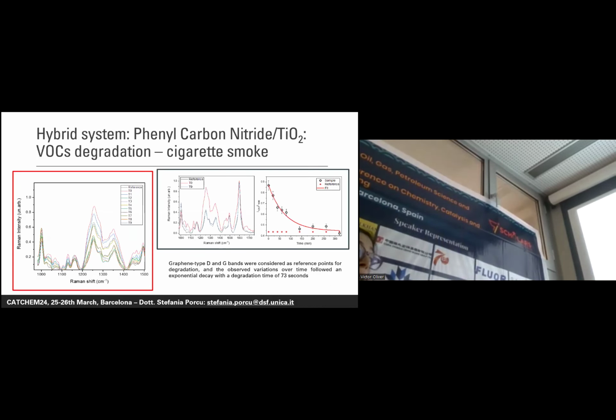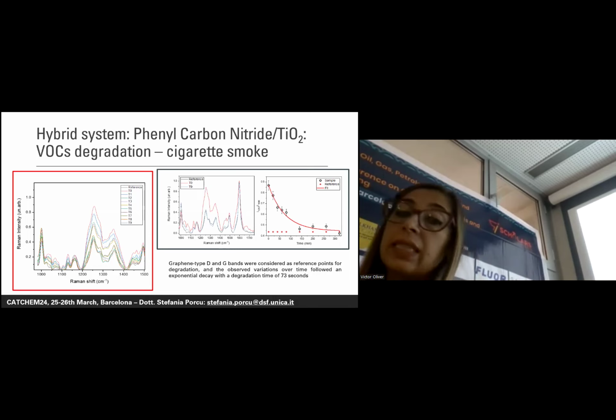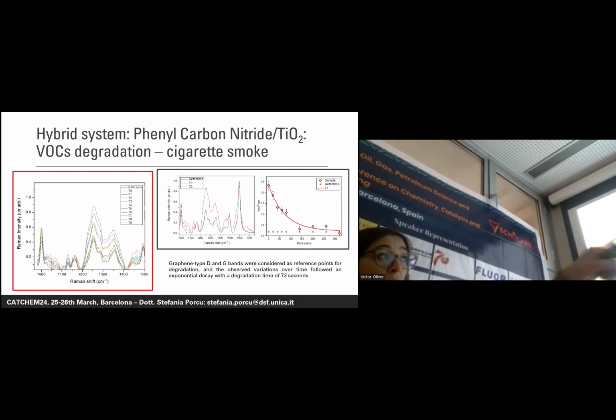We followed this study even through Raman measurements. The experiment we did was exactly the same, but in this case, we observed the variation of the D and G bands attributed to the carbonaceous residuals over time. In the graph on the right of the slide, you can see how the ratio between these two peaks decreased over time, highlighting the degradation process. And by fitting this curve, we were even able to calculate the time required for this degradation process, which for these experiments was almost 73 seconds.